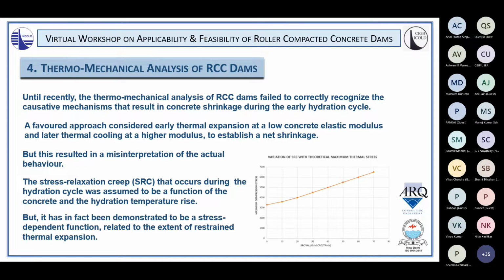And in fact, it's been demonstrated that stress relaxation creep is a stress-dependent function. So it's not just dependent on the nature of the concrete, and it will be different with different natures of concrete, as in conventional concrete, roller compacted concrete, and roller compacted concrete with different cementitious materials compositions and contents. It will vary with that, but it's not so much the hydration temperature rise that influences the extent of stress relaxation creep, but rather the extent of restrained thermal expansion. So stress relaxation creep during that hydration process is actually a stress-dependent function. It's not a temperature-dependent function. It's about thermal expansion and how much that thermal expansion is actually restrained from occurring.